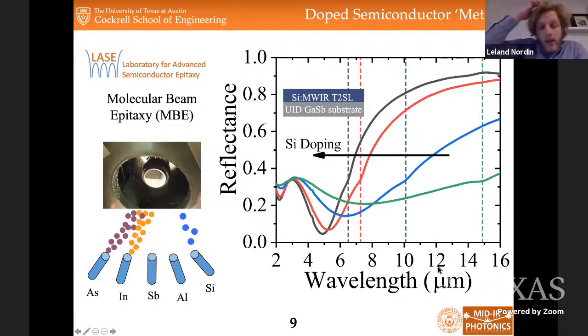And shown here is reflectance versus wavelength for a handful of these doped semiconductors. The dotted line here is the plasma wavelength, which is the wavelength at which the material turns from more dielectric-like, so you can see not very reflective, primarily transmissive, to highly reflective for these longer wavelengths and more metallic. So the plasma wavelength is right around where you can actually couple to some of these plasmonic phenomena I talked about in the beginning, the surface plasmon polariton or the localized surface plasmon.